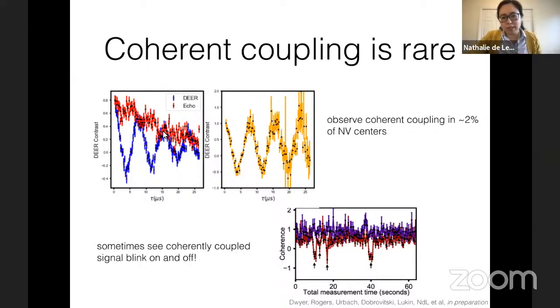And we do see this in a couple percent of NV centers, but not as often as we would expect. And so do you have a picture for what the difference is between a defect that allows you to still see that coherence, or maybe that shows you this blinking, and the ones that seem to be moving around all the time? I have a guess.